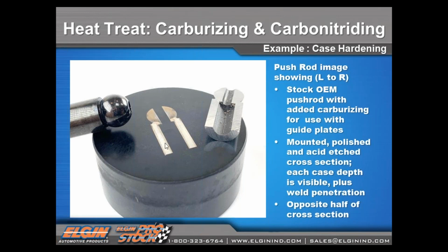And you guys have experience in engine rebuilding and things like that. We'll see that very seldom the tube may be rubbing against the guide and it's wiping the guides out, because the guides are stamped steel and they're hardened, they're neutral hardened, and the push rod carbon nitriding has actually got a higher hardness value. So it'll actually be the non-sacrificial member of that joint.